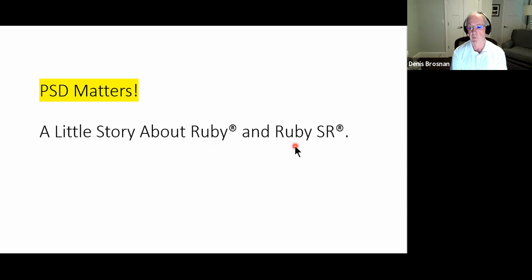So there was no thermal spalling in the product in the furnaces where it was used, or at least it was minimized. And if the story that I was told is true, and I think it is, they simply underfired the Ruby and came out with another product, which was a little cheaper for them to make, and they solved a problem with their product. They solved that problem by engineering the pore size distribution in the product. They were smart enough to do that. So pore size distribution makes a very large impact in the performance of the product.